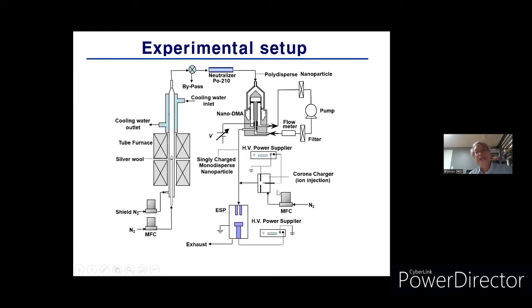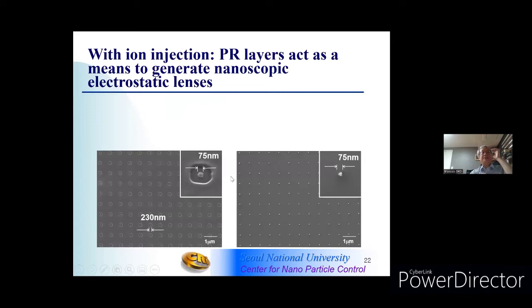We inject same polarity positive nitrogen ion together into an electrostatic precipitator chamber where we put photoresist pre-patterned silicon substrate. And this is the experimental result. You see there is no particle deposition on the surface of the photoresist.